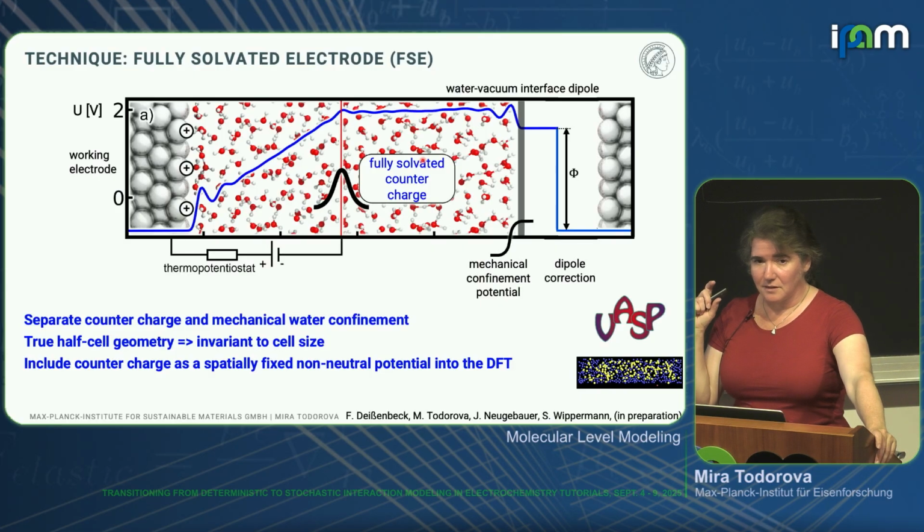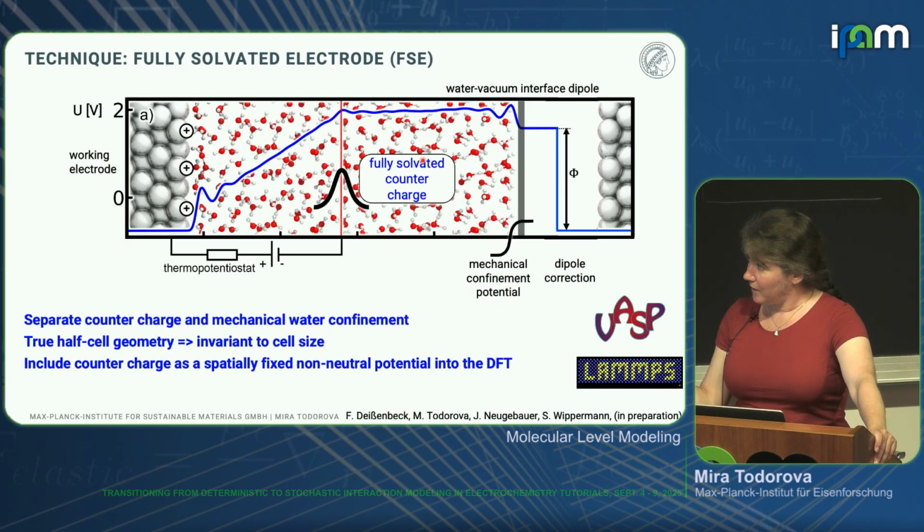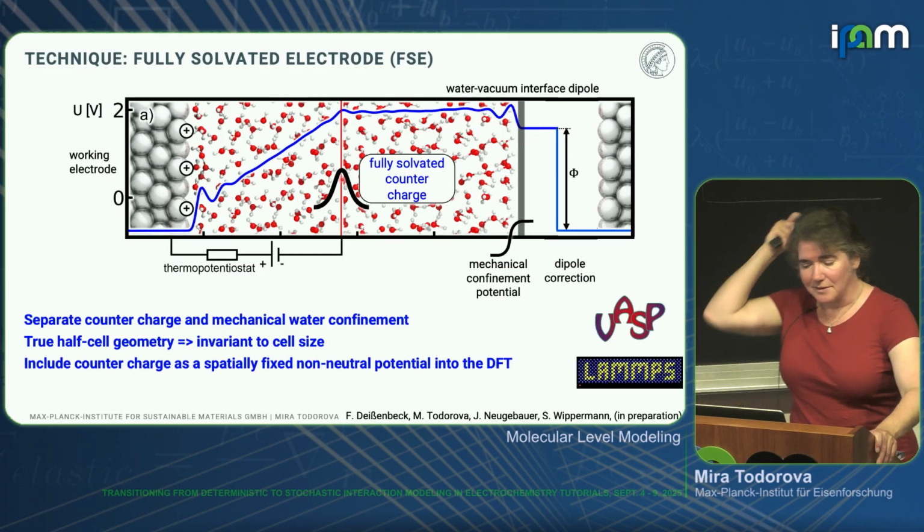Also, if you look at the surface dipole of a pristine, neat water surface, this is in the order of 0.3 eV, which is not small. And this means in a setup like we have it here, with a pristine water surface, we need to consider this 0.3 V in addition to what we have here, in order to describe our whole system.